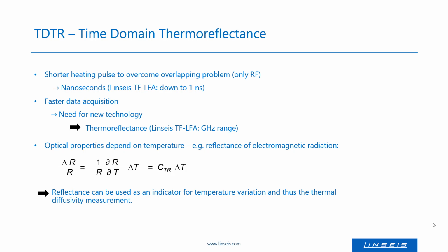For our TF-LFA setup, we use a nanosecond laser with a pulse length down to 1 nanosecond, compared to a neodymium pulse laser, which has a pulse length in the millisecond region for the standard LFA. And in order to acquire enough data points for the detection of the temperature rise on the front side, we use a faster and more suitable detection method, called thermoreflectance.